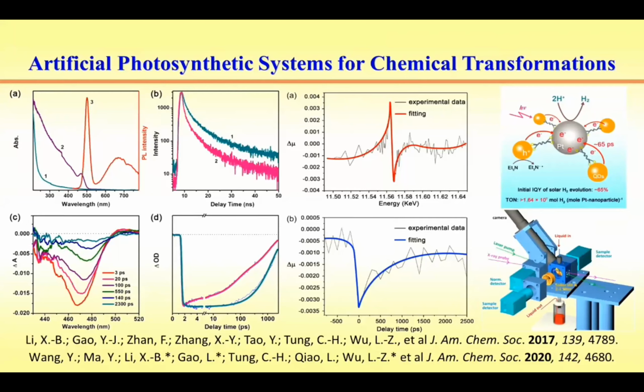How do we know that? We use time-resolved transient absorption to monitor the pathways of the photo-excited photosensitizers. As you can see, upon light irradiation, the photo-induced electron transfer takes place so fast, and the time is in the 65 picosecond range. That means the photosensitizer delivers electrons to the active site.